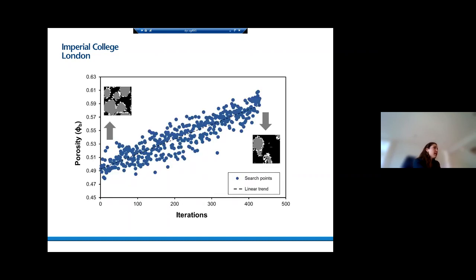We can also do that by maximizing the porosity. Well, in this case, both of them are correlated. So we maximize the relative diffusivity, and we see how the porosity of the black phase changes. And this is basically how we have managed to maximize certain properties that are of interest to our materials, basically.